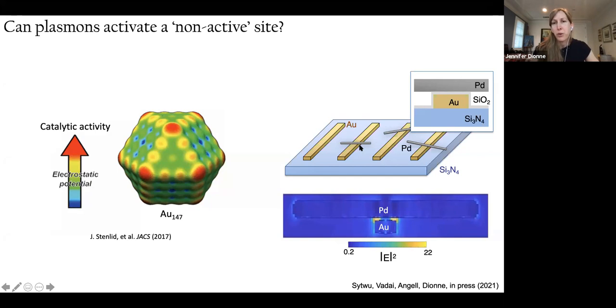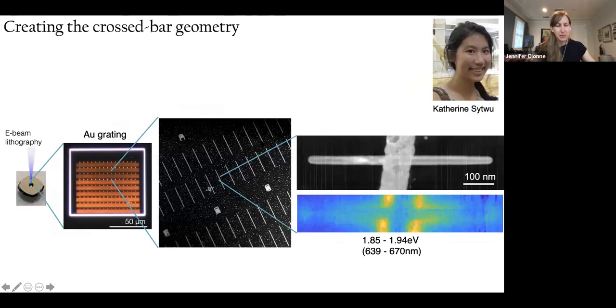So like I said, we're going to explore these palladium nanorods. What we do is put them on a gold surface, with the idea being that when you have a gold surface or a gold bar underneath, you have an electromagnetic hotspot that now corresponds with one of the faces of your palladium bar. So you might be able to induce hydrogenation at that face or at that non-reactive site. So again, we use electron beam lithography to create this crossbar geometry. We can use cathodoluminescence and electron energy loss spectroscopy to confirm that the electromagnetic hotspots are at the junction between the palladium nanobar and the gold bar that's underneath it.